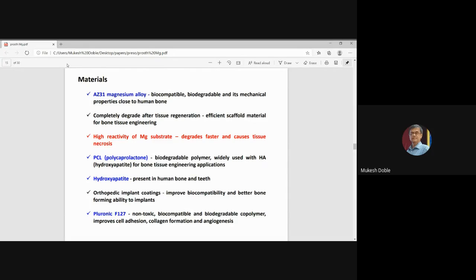And a lot of studies have been done with the hydroxyapatite, polycaprolactone combination. And as you know, hydroxyapatite is present in large amounts in the bone and also in teeth. So it's part of the human system. So many studies have been done with hydroxyapatite combination with PCL. So we wanted to reduce the degradation of magnesium, because we want to extend the life of the scaffold inside so that bone grows enough. So we reduced the degradation of magnesium by coating the surface with this polycaprolactone hydroxyapatite system. The main problem with magnesium is it can bioresorb very fast. So we created that sort of design, and we tested it for orthopedic long bone segmental defect study.